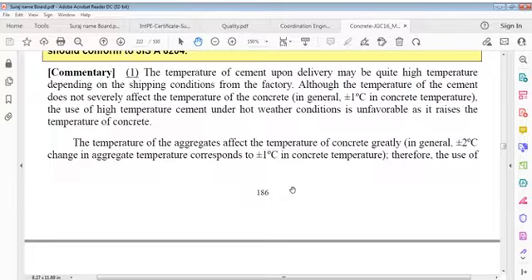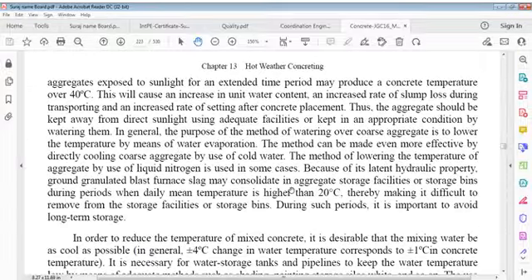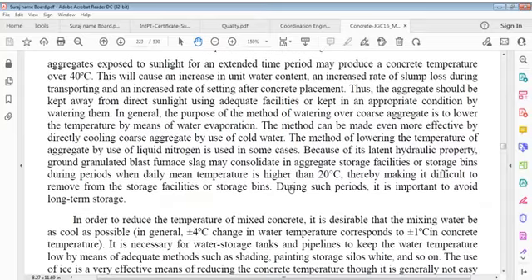Temperature of aggregates affects temperature of concrete greatly. In general, plus or minus 2 degrees Celsius change in aggregate temperature corresponds to plus or minus 1 degree Celsius in concrete temperature. Therefore, use of aggregates exposed to sunlight for an extended time period may produce a concrete temperature over 40 degrees Celsius. This shall cause an increase in unit water content, an increased rate of slump loss during transporting, and an increased rate of setting after concrete placement.